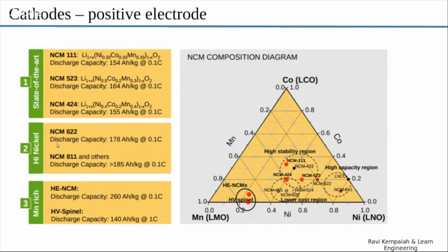The high nickel cells, which are called NCM 622 or 811, use high nickel, so 6 nickel to 2 to 2. That has 178, which is a pretty good improvement, and 811 has an even higher capacity, 185. Sorry, let me repeat it: 8 nickel, 1 cobalt, 1 manganese.